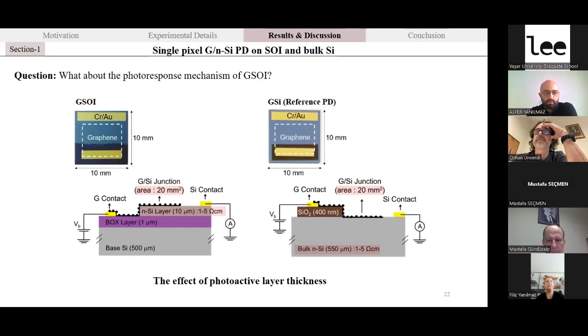Actually, as I said before, we have to compare the graphene and silicon detector array with the reference one. By the way, we fabricated the graphene and silicon-on-insulator device and the graphene and silicon device as a reference one with the same active area, and also the electrical properties of the device layer are kept constant to see the effect of the photoactive layer thickness, because we know that the only difference is the photoactive layer thickness. So we have to compare these before starting the fabrication of the array structure.